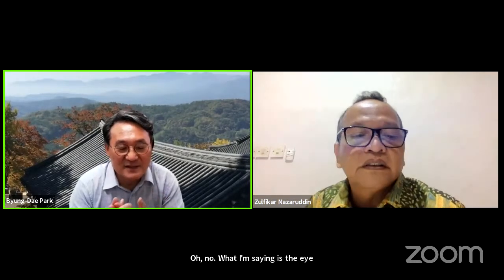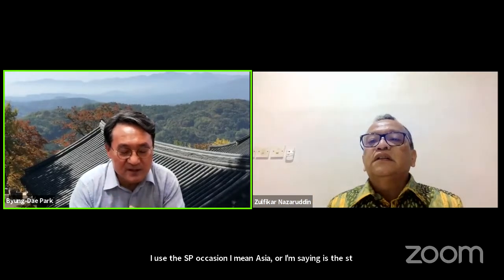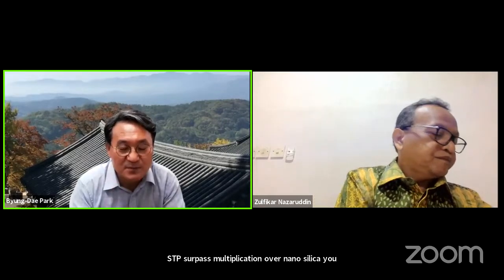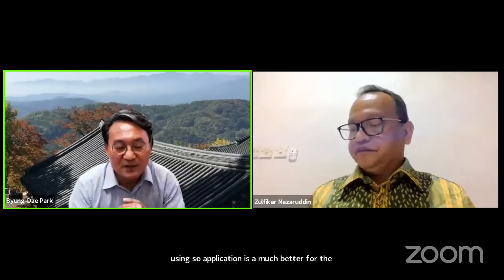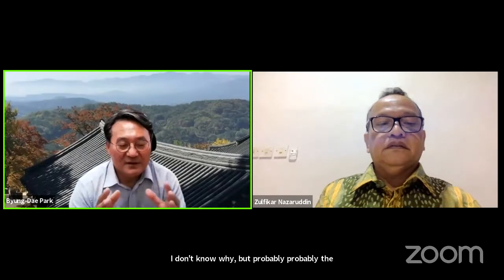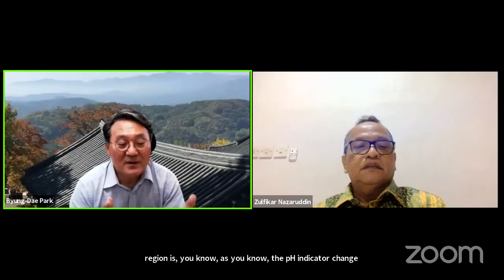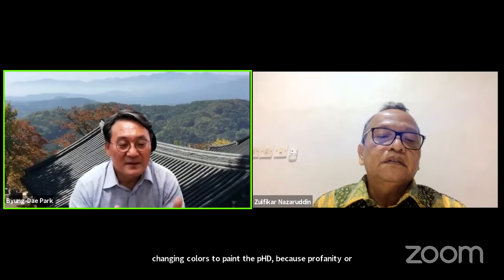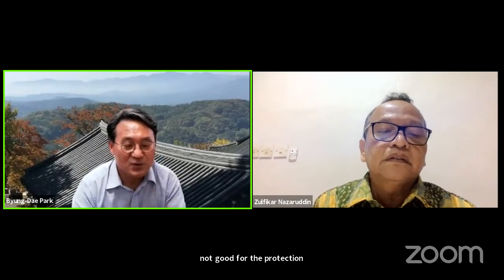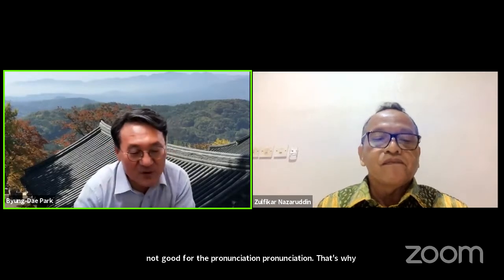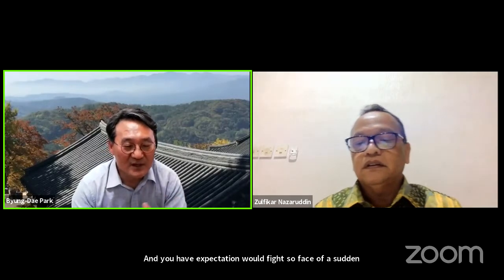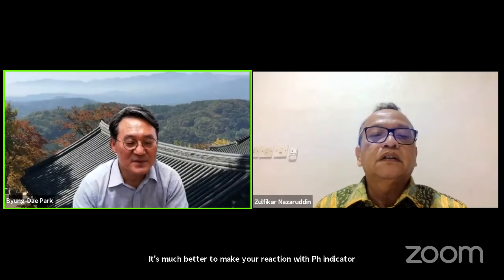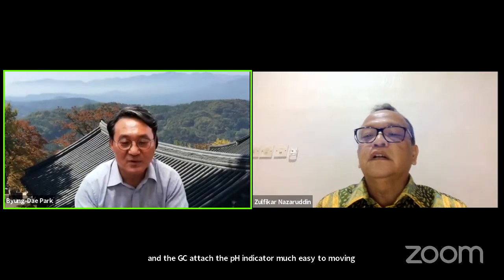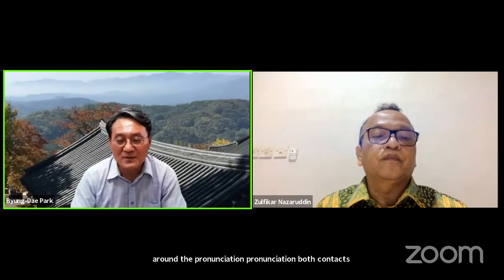Oh, what I'm saying is, I use the esterification and amination. The surface modification of nanocellulose using esterification is much better for making the reaction with the pH indicators. Amination is not good. I don't know why, but probably one of the reasons is, as you know, the pH indicator changes colors depending on the pH, because of protonation or deprotonation. But aminated CNF or CNC is not good for the protonation. That's why they're not good for the color changes. But when you have an esterification-modified surface of cellulose, it's much better to make a reaction with the pH indicator, and with this attachment the pH indicator is much easier to move around for deprotonation, protonation, those kind of things, and then gives a good color change. That's what I think.